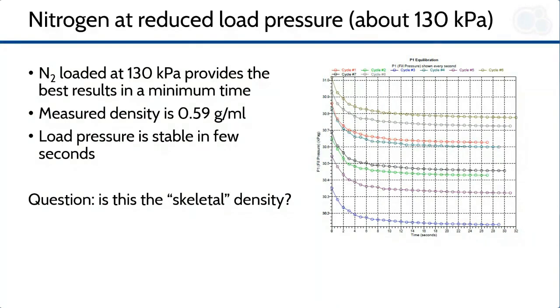In this case, we obtained a density of 0.59 grams per milliliter, that is a relatively low value. Is this the real skeletal density, or did we measure a sort of apparent density? If helium is diffusing slowly into the coffee granules, it might be possible that we have something like a closed structure. What we measured with nitrogen at reduced pressure is not the real skeletal density, because it might be excluding some closed cavities that nitrogen in these conditions cannot fill. We must investigate more.